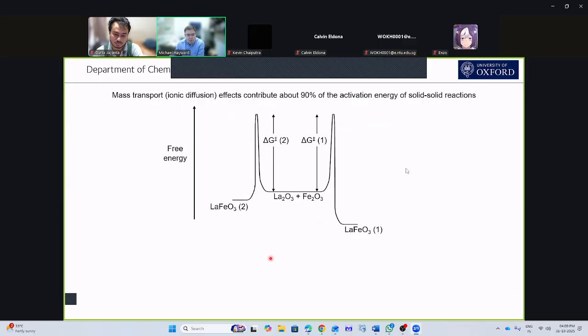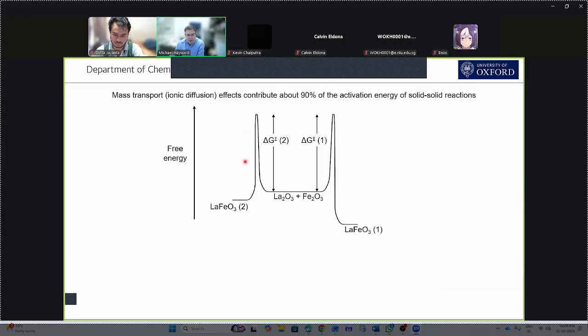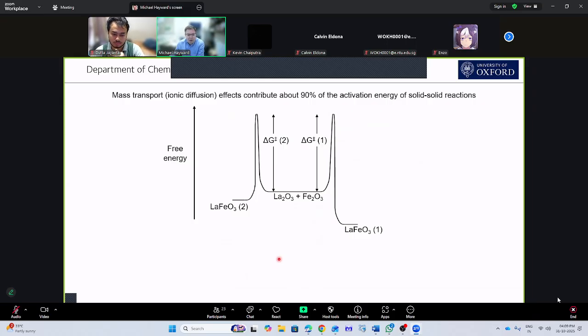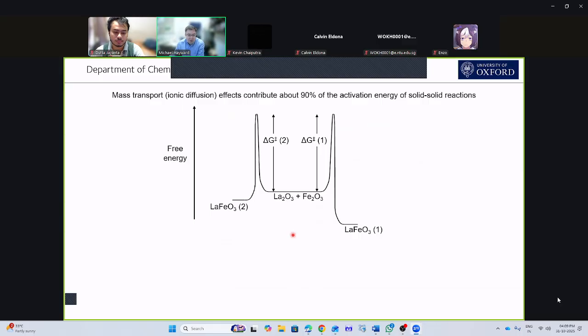And this presents us with a problem, because if I supply enough energy to make form number 2 to get over this barrier, I've also given the system enough energy to get over this barrier. And so what we find is when we heat the system up, the two products enter a thermodynamic equilibrium, and actually an equilibrium with all the other possible products. And what we find is we make the most stable phase or combination of phases. And so under these conditions, we really can't make metastable phases here. So of that big combinatorial array of possible compounds we were thinking about earlier, I'm only going to be able to make a small subset of them by this route, because I can only make the thermodynamically most stable ones.